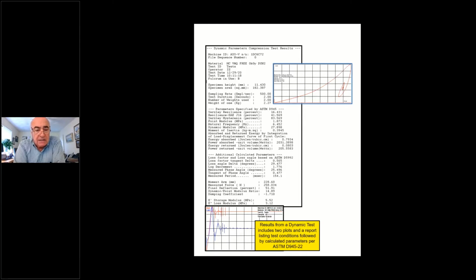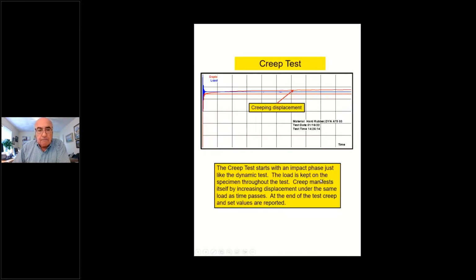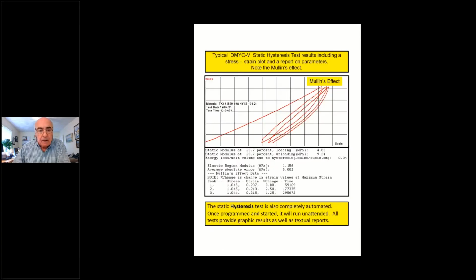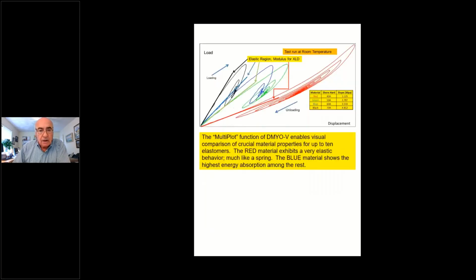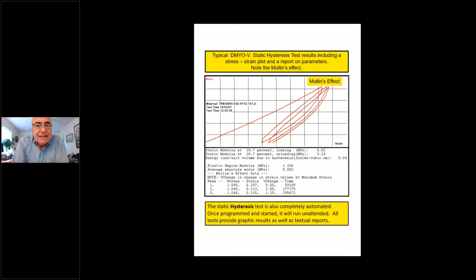Damping coefficient is. We also calculate E prime storage modulus, E double prime loss modulus, and E asterisk, which is the complex modulus out of those. This is for compression. We also report G prime, G double prime, and G asterisk for shear tests. Then we go to the next test.